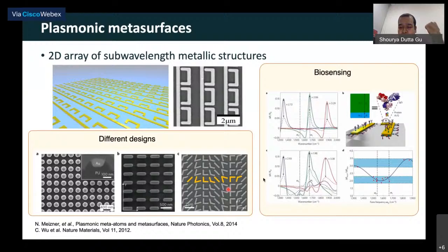Now, this is another example where they have used this kind of structures for doing biosensing. So what they're doing in this particular work is that they're looking at the orientation and the thickness of a single layer of molecules, right? So just remember, a molecule that is used in this particular study is around 2 to 5 nanometers. So it's very, very small. So here what they're doing is they're precisely measuring the exact thickness and the refractive index of that single molecular layer that they are putting on the structure, right?